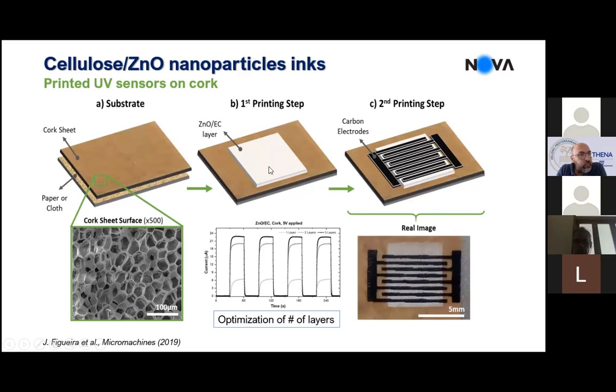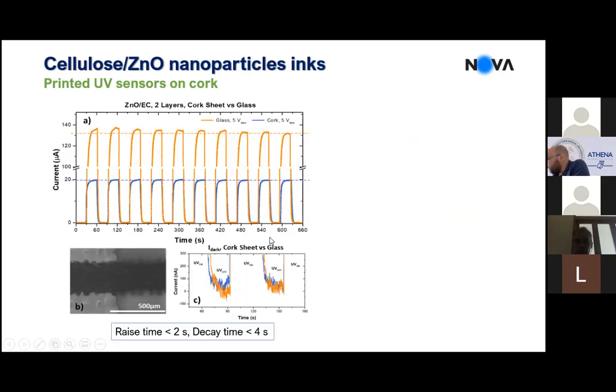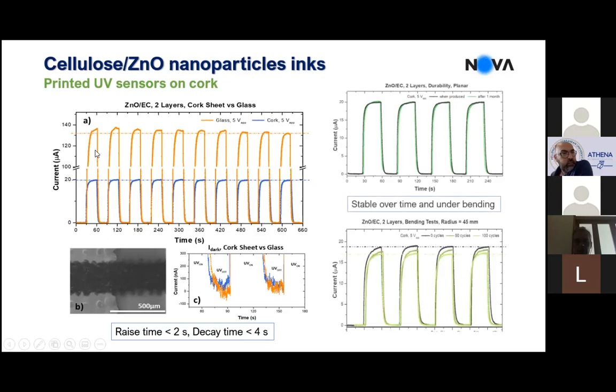And so we need to adjust the thickness of the sensitive layer to get the proper response from the UV sensors. You can compare, of course, how they respond comparing with sensors printed on glass that are much smoother. They don't perform so well as those on glass. We know that, but what is nice is that they can be bent, and in glass you cannot do that. And you see how they behave after bending cycles, and so with a small degradation, of course, but not very aggressive degradation. So it is within 10% loss in the maximum current, in the sensitivity that you get in these UV sensors.